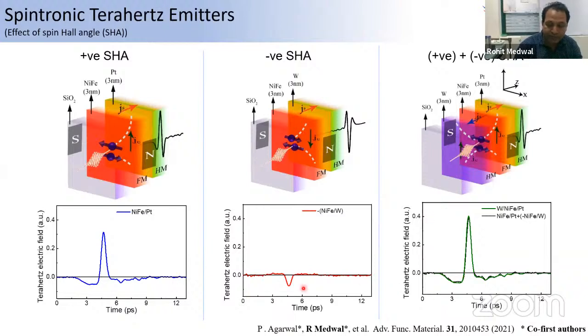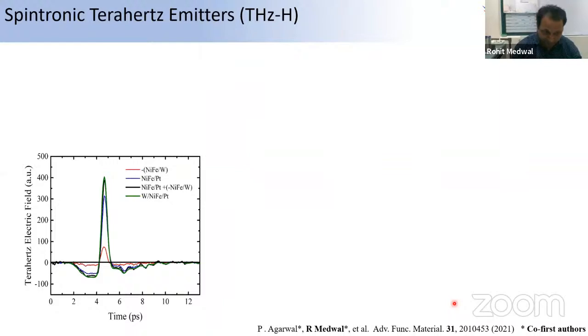And we can add up these two signals by interfacing platinum with the permalloy on one side and tungsten with permalloy on the other side, so that the direction of spin current is reversed. The net effect is that if you vectorially add all the spin current and charge current, you will see that both are in the same direction, so this effect is additive. So this clearly shows that you can add the M, because M, magnetization, is a vector, and you can also change the phase of the terahertz photon by changing the spin Hall effect of the tungsten and platinum.